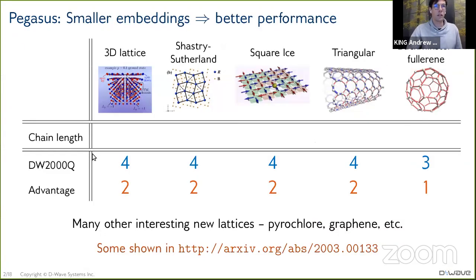Okay, so what can you do with this graph? I'm going to focus on some finite dimensional systems that we have simulated in the previous system. For all these except for one, the new system allows embedding with chains of length 2 instead of chains of length 4. This started with Richard Harris et al.'s work on the 3D lattice. And we've studied a lot of two-dimensional systems in the meantime, including the Shastry-Sutherland lattice with Oak Ridge National Lab, quantum artificial square ice with Los Alamos National Lab, order by disorder and topological phase transitions in a quasi-triangular frustrated lattice. And one that nobody has looked at, as far as I know, is Buckminster-Fullerene, which you can actually embed with chains of length 3 in the D-Wave 2000Q processor.